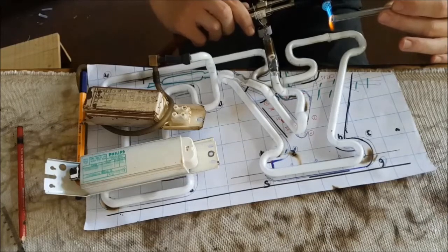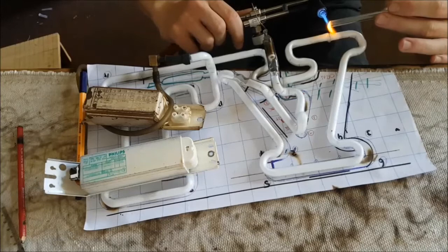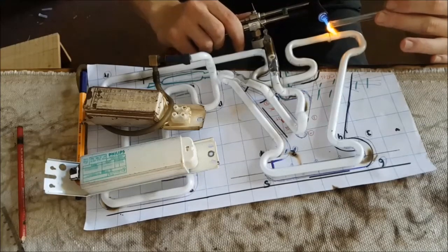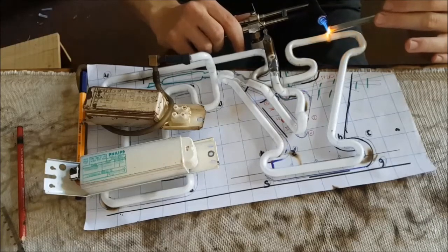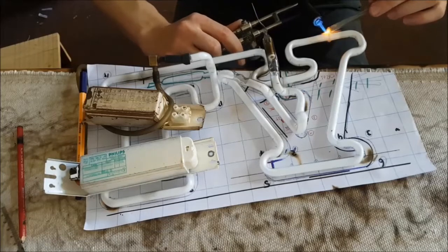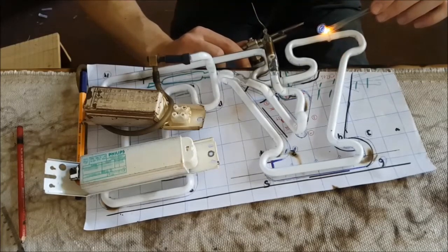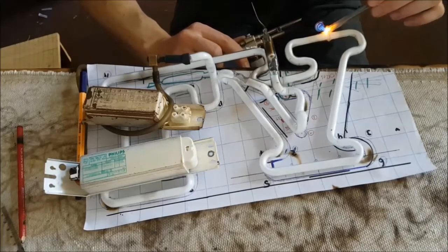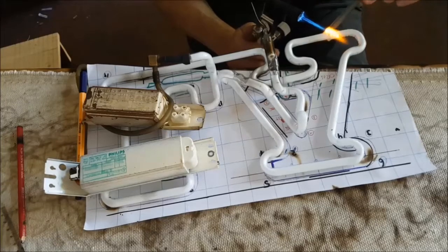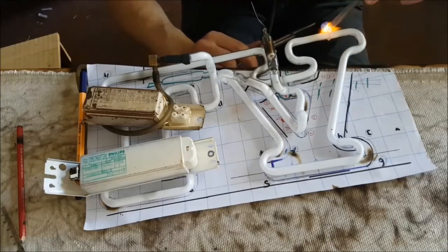Well, I didn't have a thin tube ready, so I just grabbed the next piece of glass that I could find and try to melt off a little drop of glass of that. But I just have no experience in this kind of repair and quick fix. So you see that I kind of got stuck with the glass. It cooled down too fast and too much of the tube melted off and stuck to that weld. So now I'm trying to get the tube off the weld again.